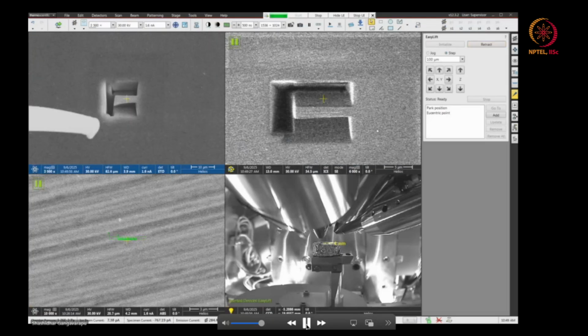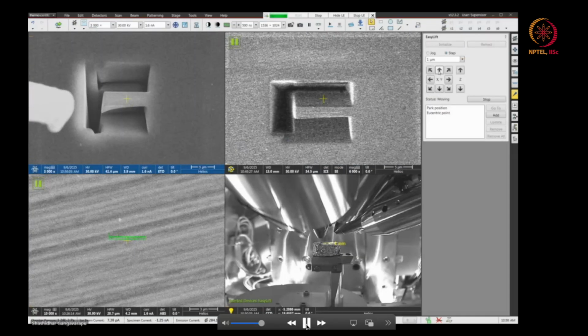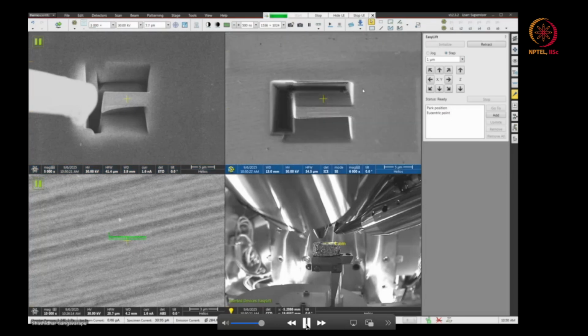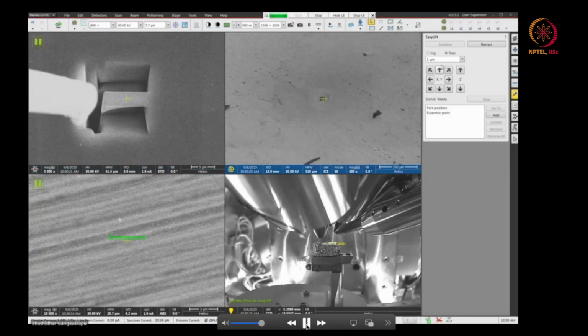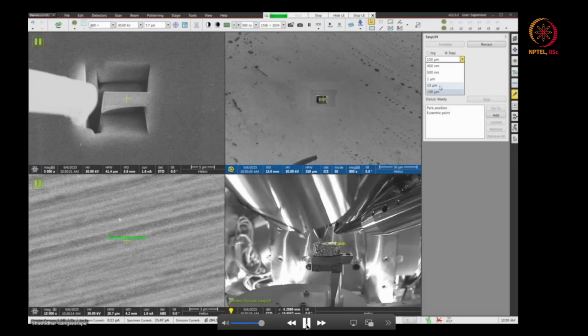Now I insert the manipulator. Now you can see in the E-beam window our manipulator is there. That white color is basically our micro manipulator. Now in the E-beam window we basically align the XY. So in the E-beam window you can see the XY movement. You can align XY. I am using this XY movement to align my manipulator with our sample, and my manipulator and my sample should align perfectly. You can see in the E-beam window it is aligned perfectly.